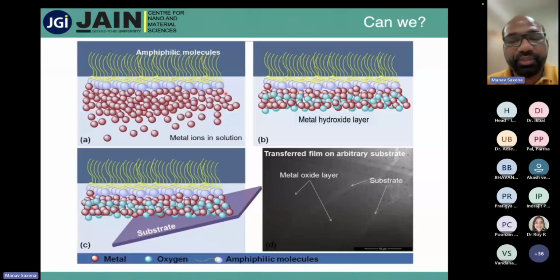Here we have come up with a method where we use amphiphilic molecules and a metal ion solution, and we make a reaction where we reduce only the metal ions present at the solution and air interface. We are not reducing all the metal ions in the solution. We are reacting only the metal ions interacting with the amphiphilic molecules at the solvent and air interface, and we can get a metal hydroxide layer which we can scoop onto anywhere.